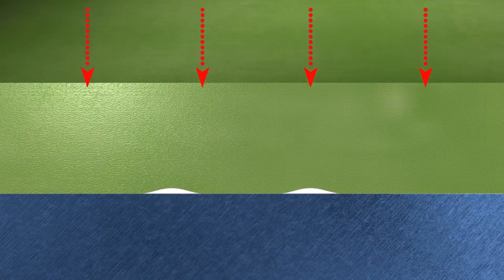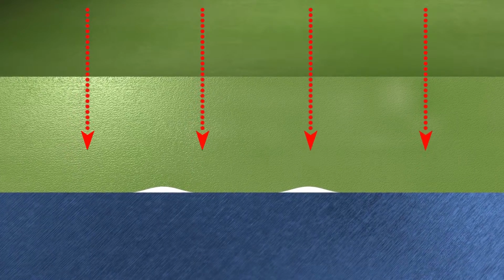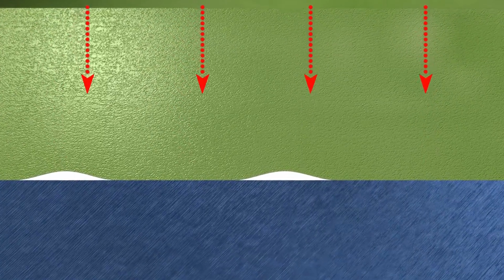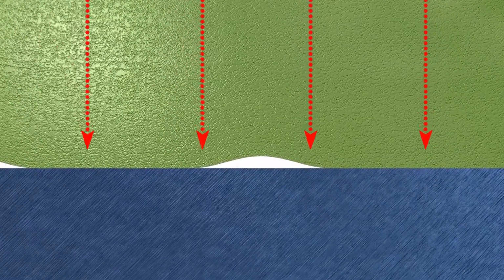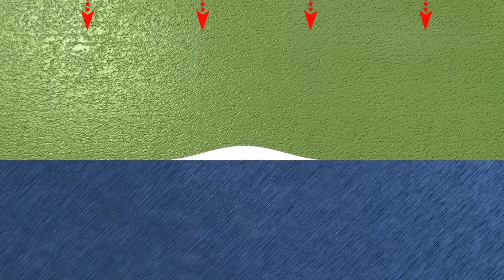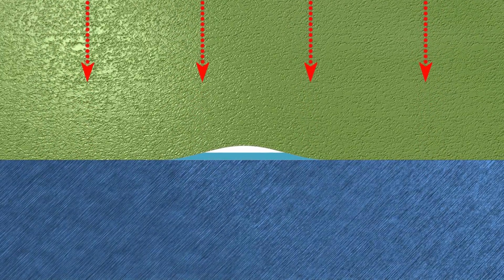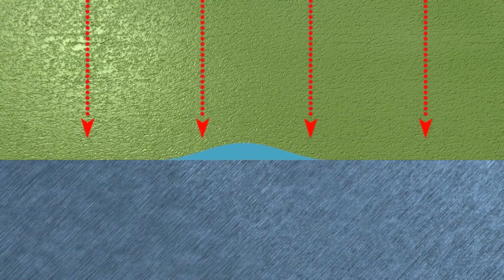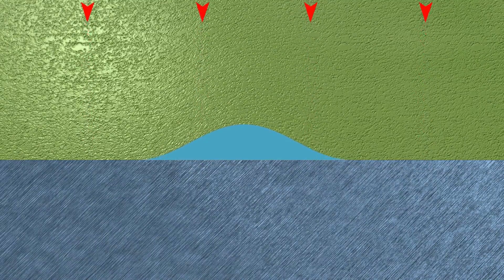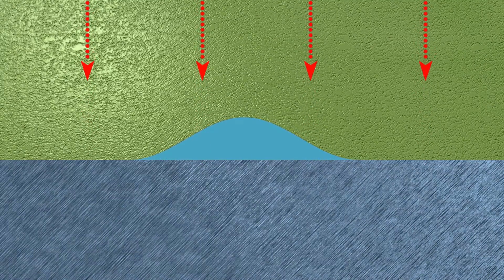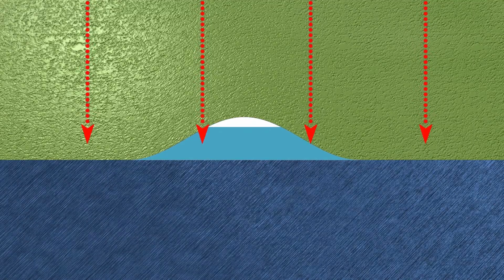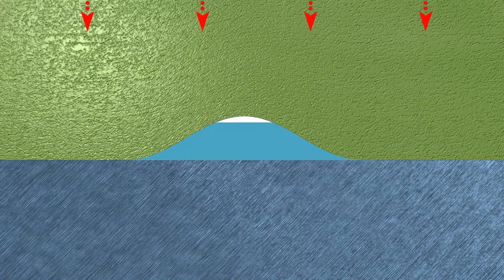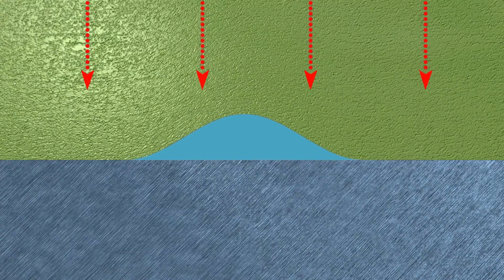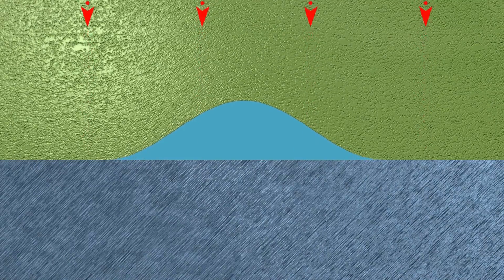If moisture vapour gets down to the substrate and it is cold, there will be a condensing effect that causes vapour to form liquid in microvoids. Once formed, any small temperature movements in either the process or atmospheric conditions will cause that liquid to expand or contract. When it expands, it will push the coating away from the substrate, and then if it contracts again, it will allow more space for more water vapour to condense, and it becomes a self-propagating blister.